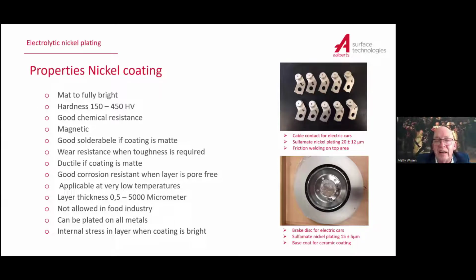And the advantage of this ductile coating, they offer matte coatings, they're very ductile. That means you can bend, in principle, the coating around an axis of 5 or 10 millimeters, and you can bend completely around without getting any, I must say, not scratches, but, I don't know the English word, sorry. I come to that. Good corrosion resistance when the layer is pore free.